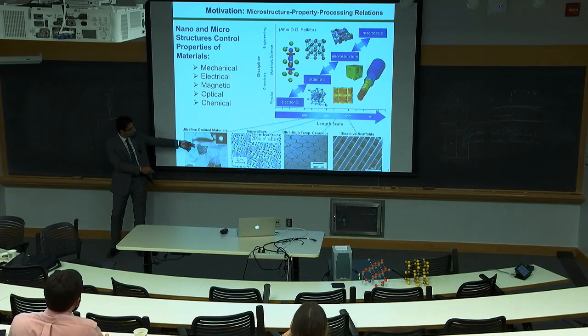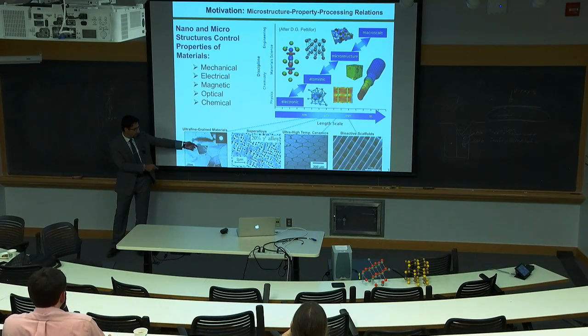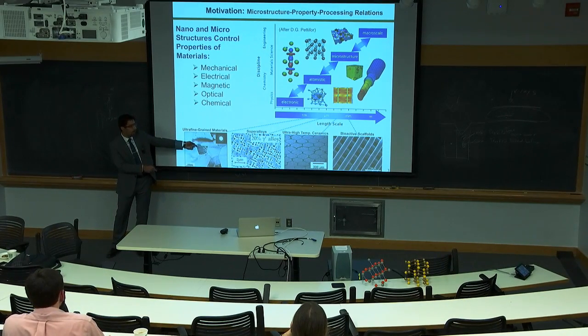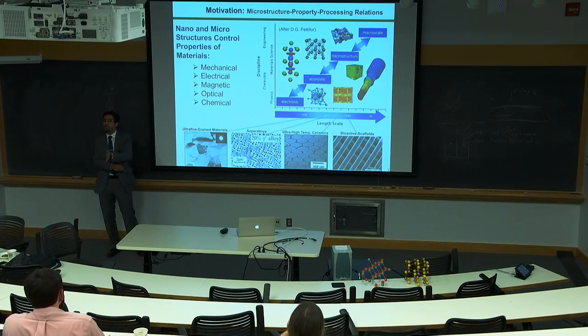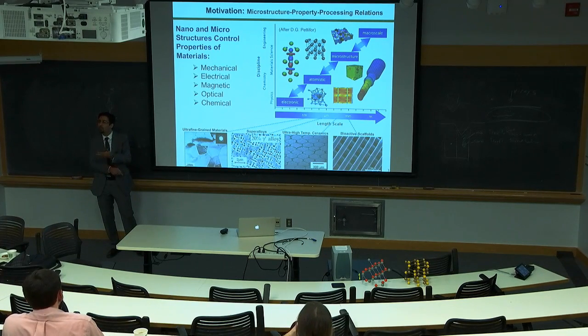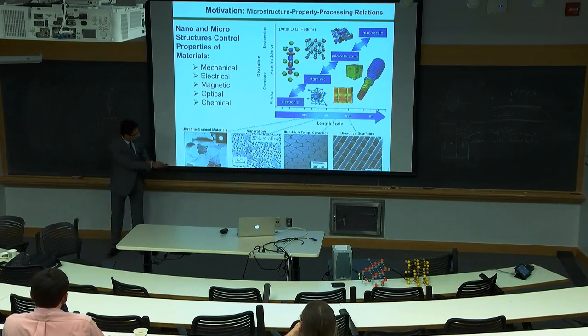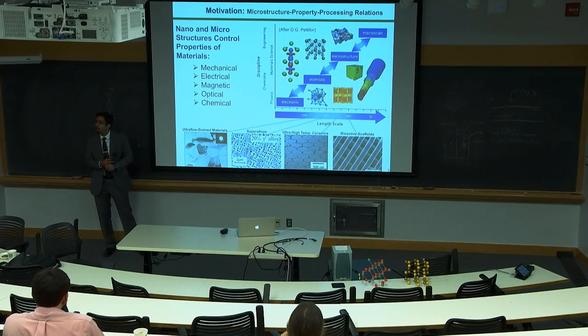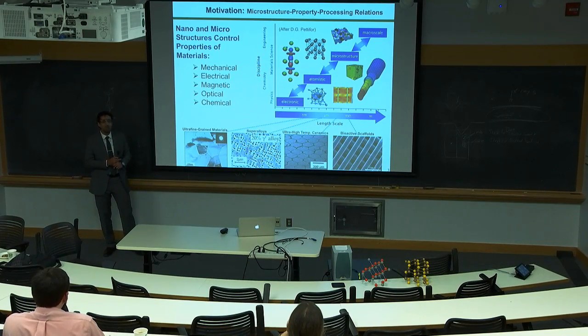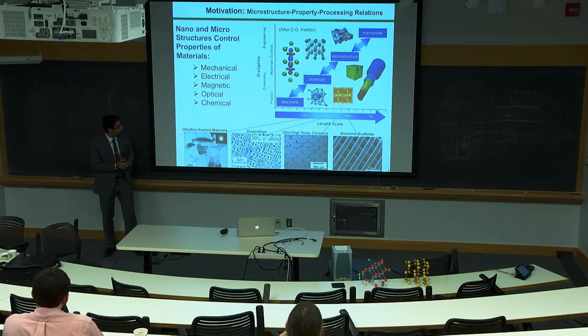Going to a little bit higher length scale, 2 microns. So these particles, these black particles, this superalloy is a nickel-based superalloy to make turbine blades of jet engines. The size, shape, and volume fraction of these particles determine the rupture life of turbine blades.